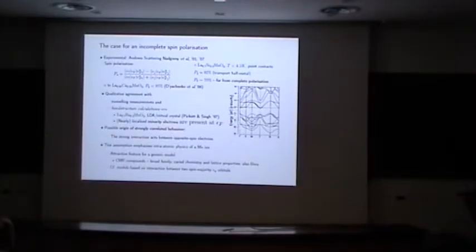There is also experimental evidence pointing at the presence of spin-minority carriers there. It comes from point contact Andreev reflection scattering. You can define the quantity Pn, which is the ratio here. You see density of states for two spin components are weighted with corresponding Fermi velocities. And if you calculate Pn without any Fermi velocity, you are fairly far from complete spin-polarization, it's 78%. If you weigh with the Fermi velocity squared, which is what enters the transport, you are nearly completely spin-polarized. So people suggest calling it transport half-metal as opposed to simple half-metal. You still have spin-minority states in the Fermi surface, although they don't contribute much to the transport.